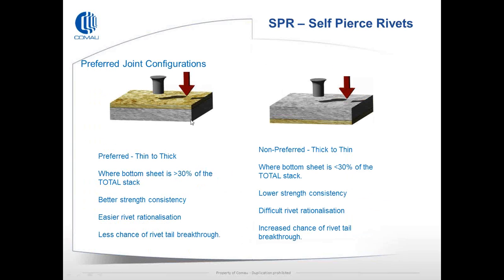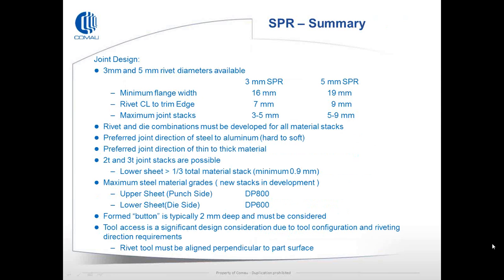Here we have some preferred joint configurations. Preferred is thin to thick, where the bottom sheet is greater than 30% of the overall stack, which gives better strength consistency. Non-preferred gives a lower strength and also sometimes causes, in terms of the rivet, breakthrough on the lower edge, which obviously then gives a quality problem.